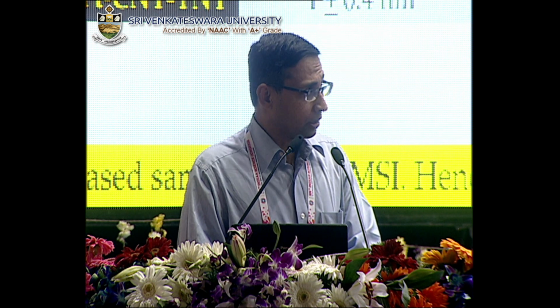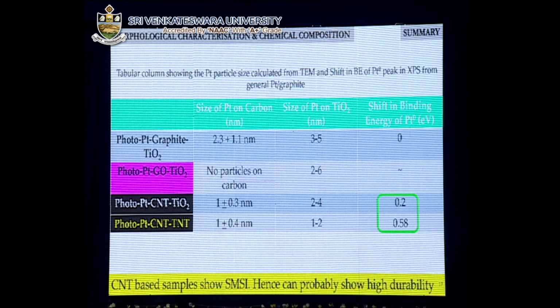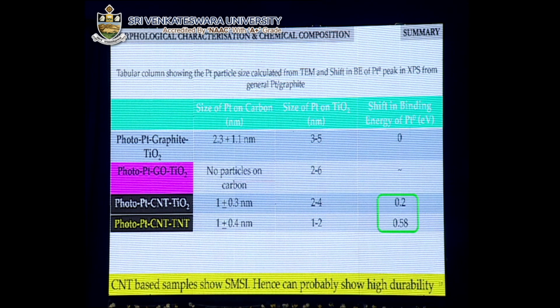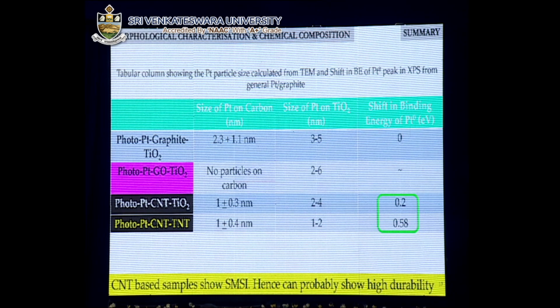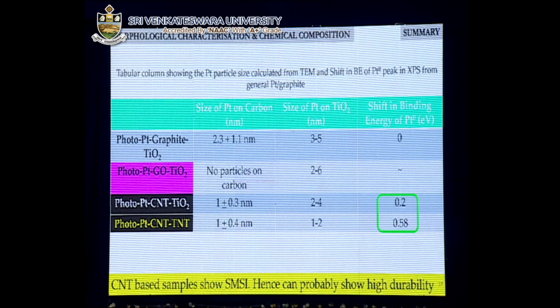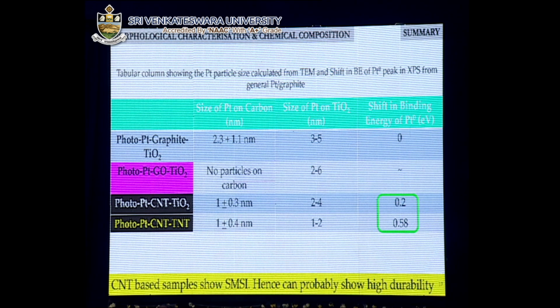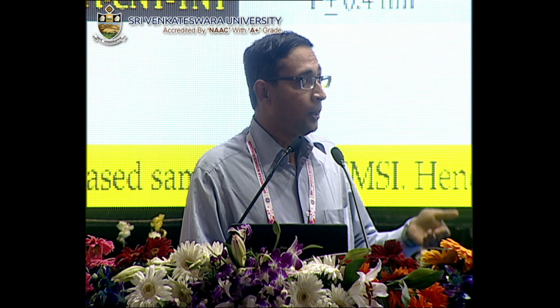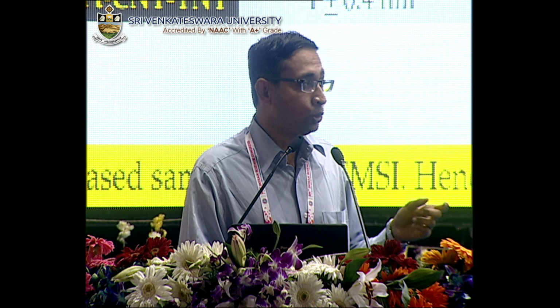So here is a summary of all the samples which we have made, and as we see, the photo-generated platinum on graphite showed a platinum size of around 2.3 nanometers on carbon, and the size of platinum on TiO2 was around 3 to 5 nanometers. That is, we now have two types of platinum: one studded over the photocatalyst and the other studded over the carbon. The particle size of the platinum studded over TiO2 is bigger than that on the carbon.